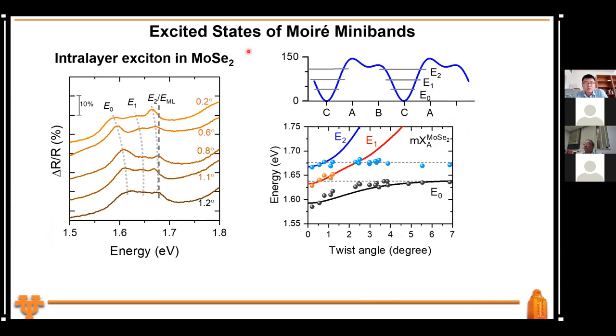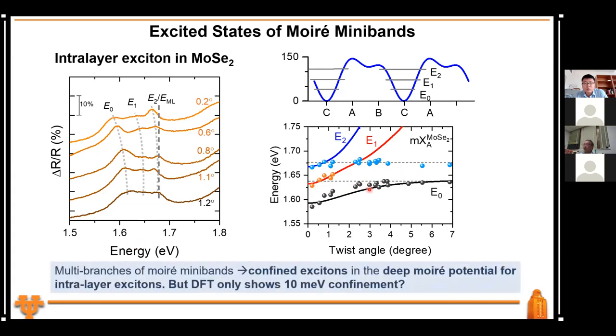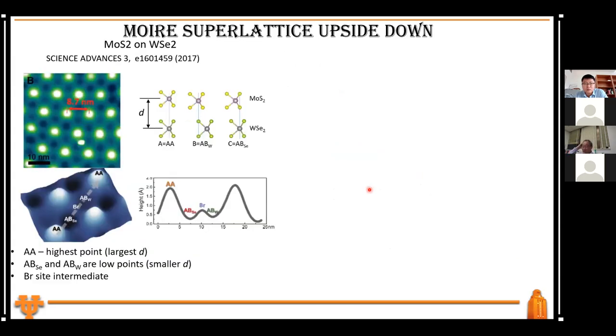Not only that, if you do absorption spectroscopy, you will be able to measure the intralayer exciton excited states. So you do this kind of absorption spectroscopy, then you see all different kinds of levels as a function of twist angle. Then you measure it, and these are these levels, and it turns out you can fit it. The fact that you can see multiple branches means confined excitons. These are confined excitons in a very deep moiré potential for the intralayer exciton. But the DFT only shows such a small confinement. Where could it go wrong, right?